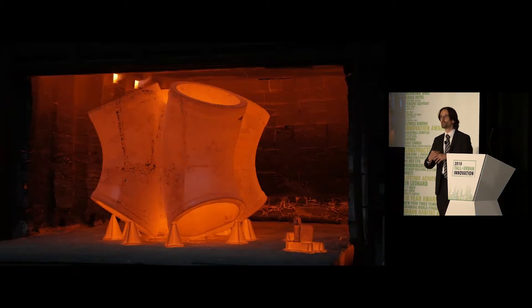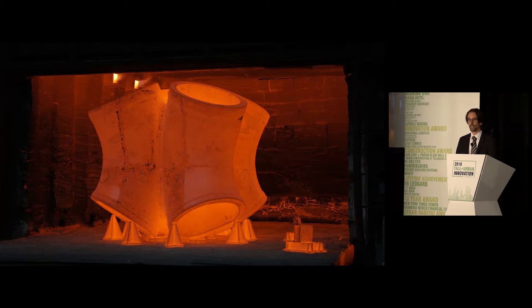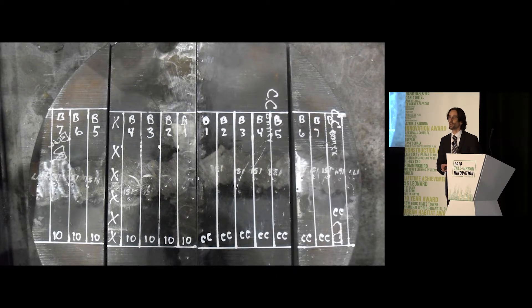Another step in our manufacturing process is to fully heat treat and stress relieve these components so they're fully isotropic, with no potential for residual stresses that can be built into complex fabricated connections. We've put thousands of castings into use in hundreds of buildings all over North America. We've done very large connections — for example, a cast node designed for the Transbay Transit Center in San Francisco featured a five-foot solid steel section, and we know those mechanical properties are achieved because we've destroyed castings of that size, sectioned them, and confirmed we can get the mechanical properties all the way through the thickness.